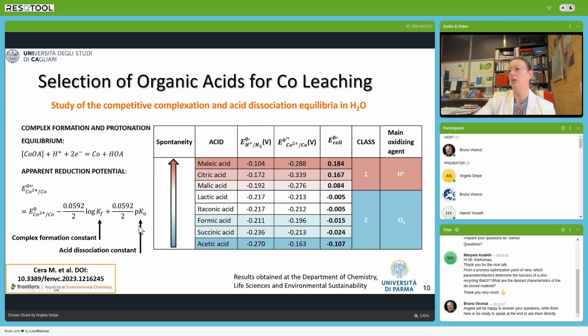Instead, acids with a higher pKa, if we are speaking about the minus log of the constant. Of course, when we have a lower pKa, we have a stronger acid. So I can summarize: when we have a lower pKa and a higher K formation for the complex, we have a stronger acid, so a class 1 acid that can behave like an oxidizing agent. When we instead have a higher pKa and a lower Kf, we have a class 2 organic acid that does not behave as the main oxidizing agent in the solution.